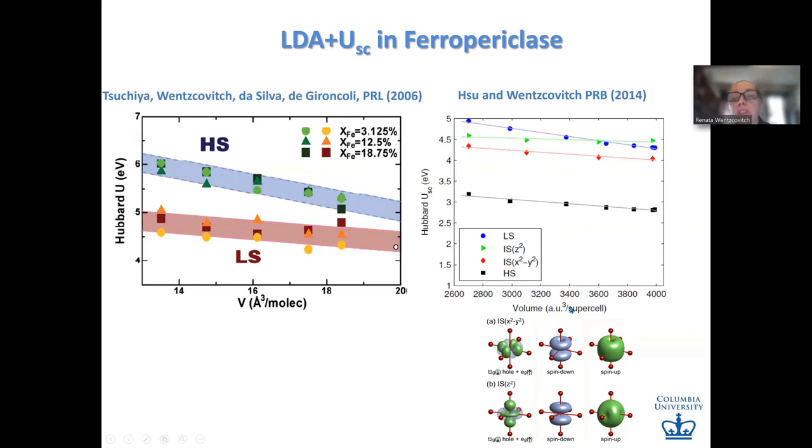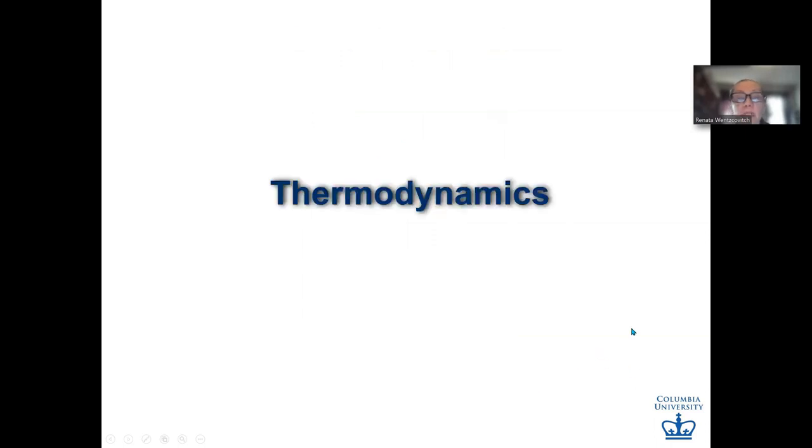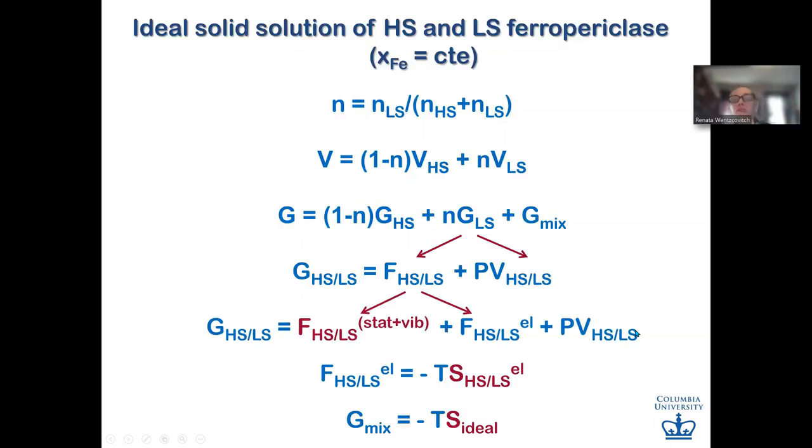So here you have intermediate spin states too, with their own U. This is the transition enthalpy change with the self-consistent U, about 71 GPa here. And this is where the intermediate spin states are. They are metastable states and they are essentially not populated.